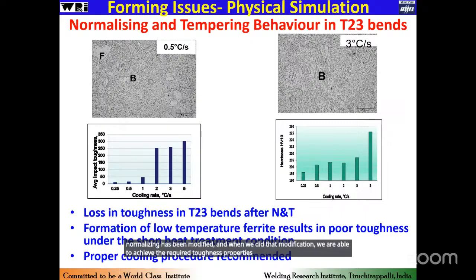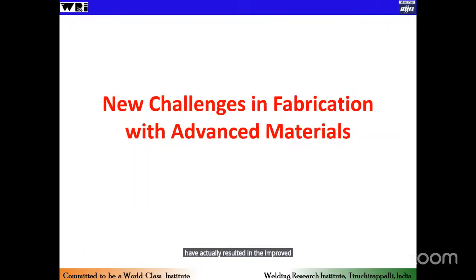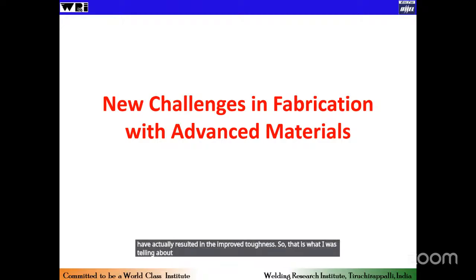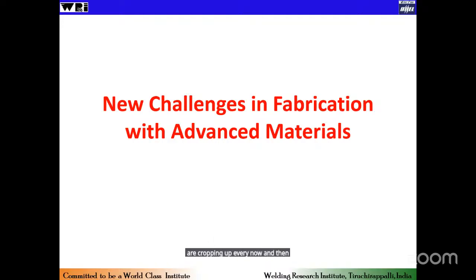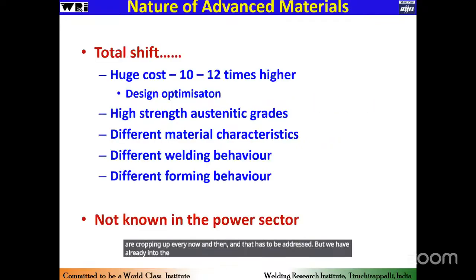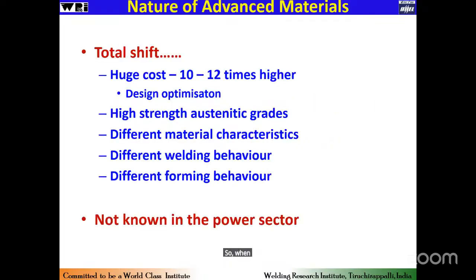As you can see, the microstructural difference between cooling at 0.5 degrees per second and 3 degrees per second, the change in the microstructures, has resulted in the improved toughness. So that is what I was telling about the older materials. The challenges are cropping up every now and then, and that has to be addressed. But we are already into the advanced materials. So when we talk about the advanced material, there is a total shift.